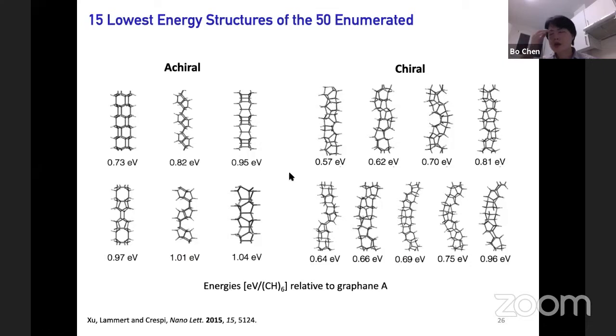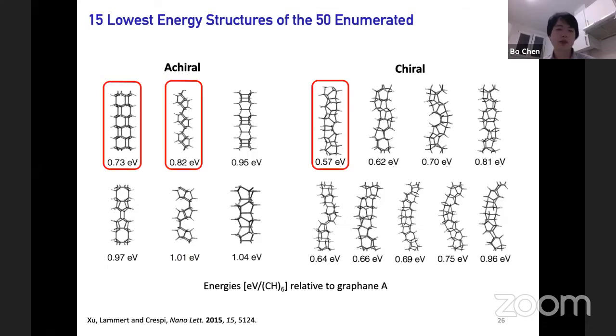Remember that we talked about the 3 predicted nanothread structures, they all come out in this enumeration, which is very nice. And this is polytwistane, the helical one, which turns out to be the lowest energy thread among the degree 6 threads.